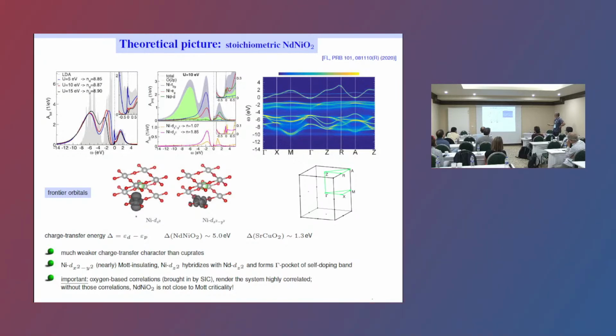But the main result is that, as Carsten was always saying, whereas the cuprate is strongly charge transfer-like with a very small charge transfer energy of 1 to 2, the nickelate is not, it is like a Mott-Hubbard system. And this is severe because now all the transport is mainly affected by this. We know Mott-Hubbard systems from the early transition metal oxides, where we have t2g systems, which are multi-orbital already. And that is fine. You put a hole in, and the t2g do not hybridize super strongly with the oxygens. Anyway, they are threefold. So the hole can propagate in these t2g for the early transition metal oxides if they're correlated or also Mott insulating.